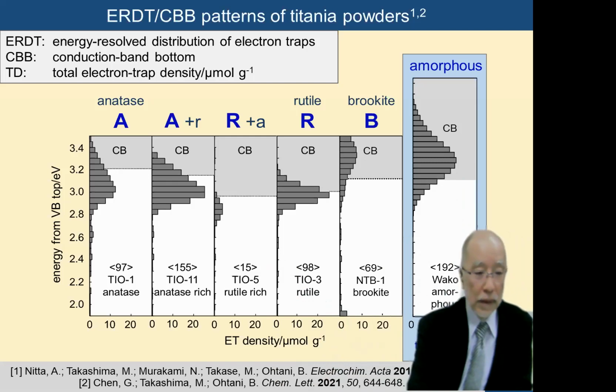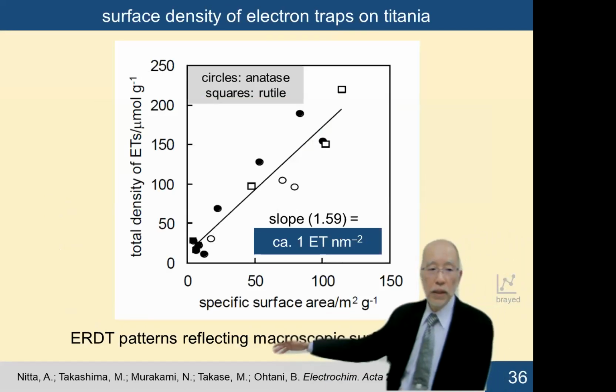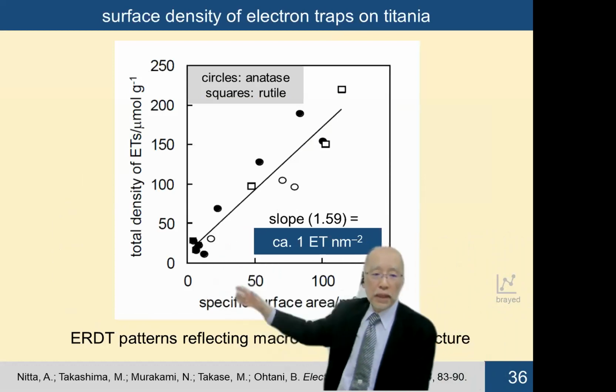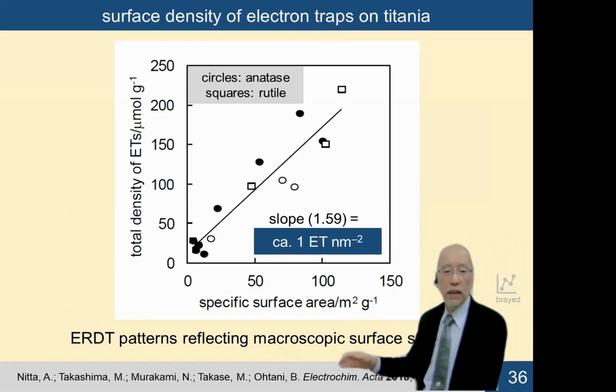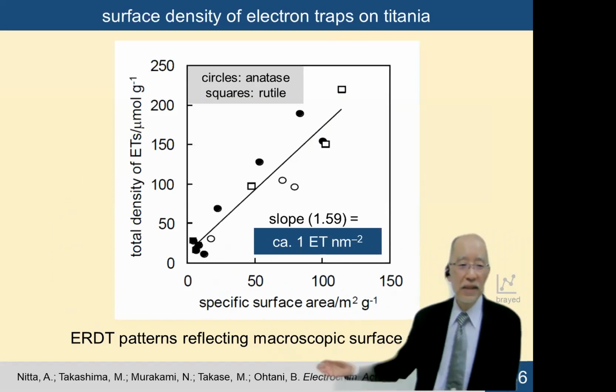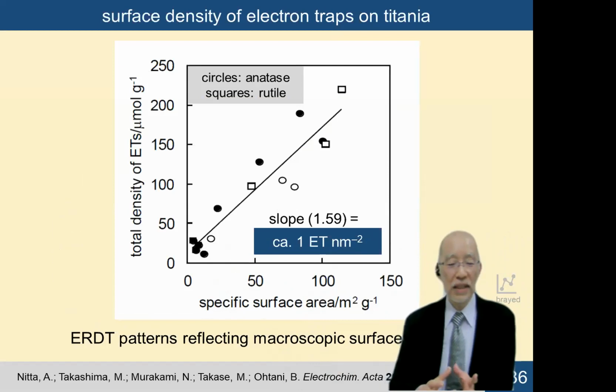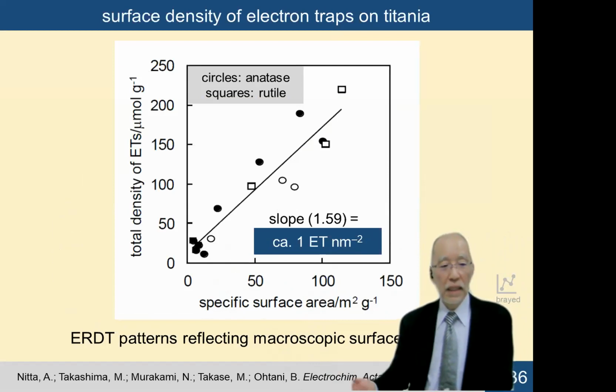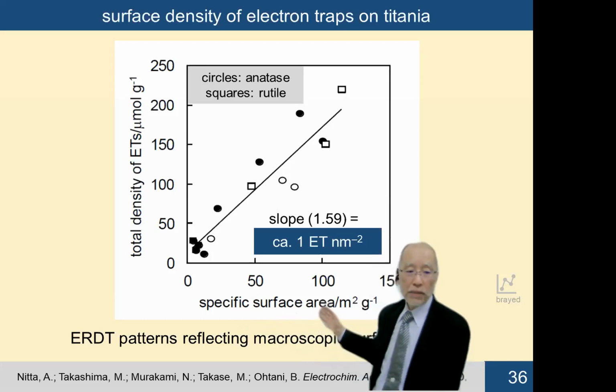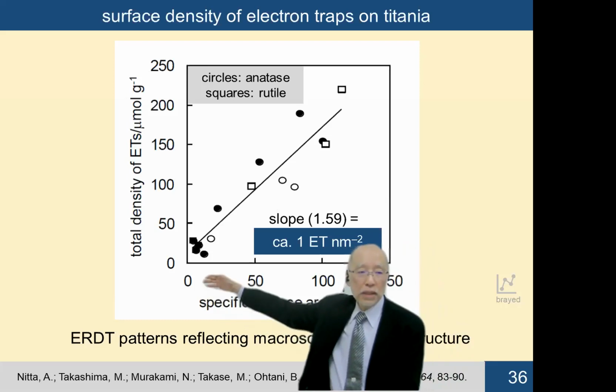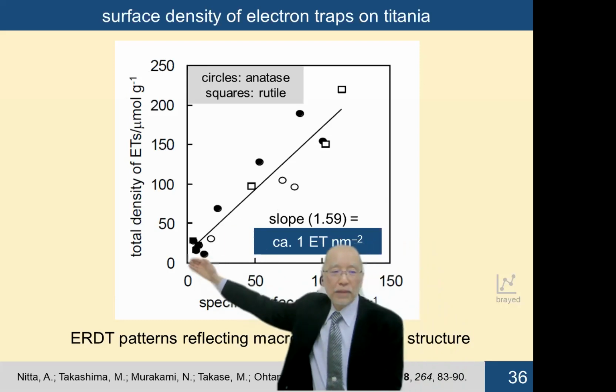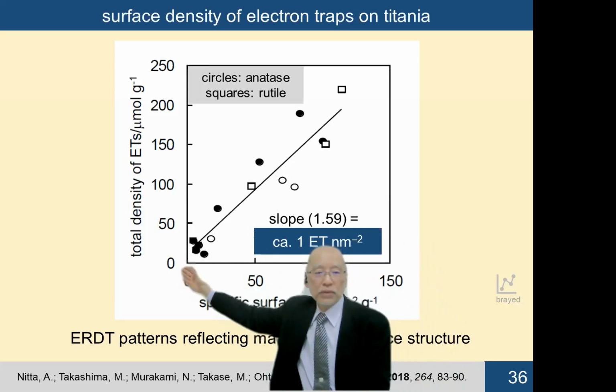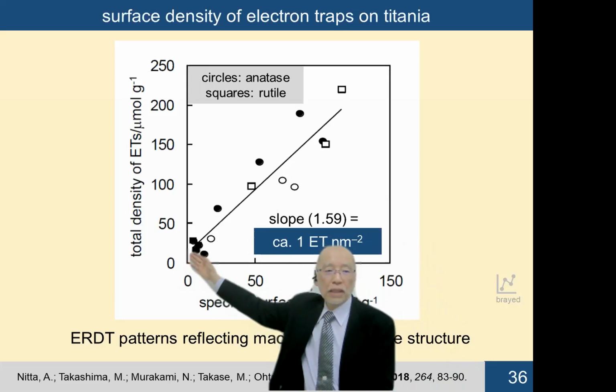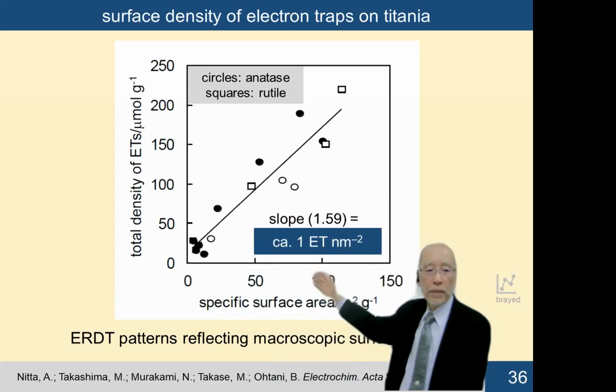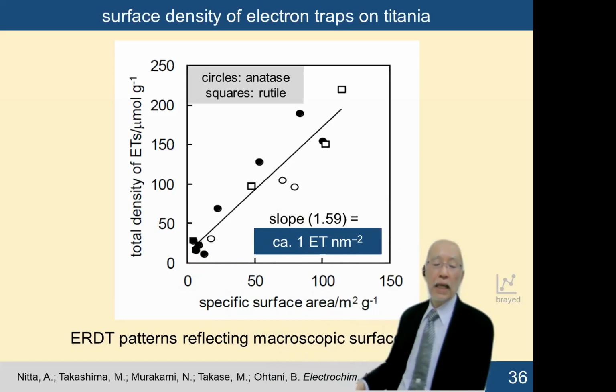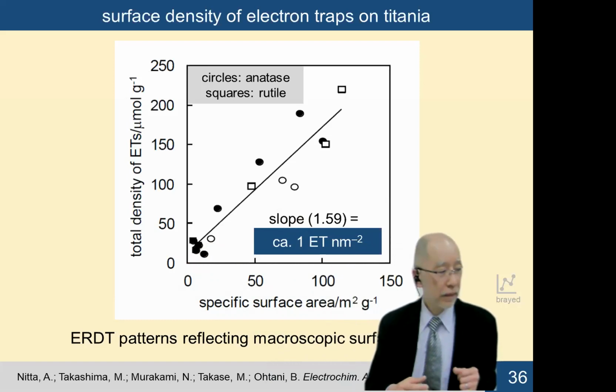Another important point is if the total density of electron traps is plotted against specific surface area, I cannot say that is a good linear relation, but actually the tendency is clear. With increase in specific surface area, the total density is increasing. And there is some y-intercept here, not completely zero, but almost zero. And the slope tells that about 1 electron trap per square nanometer.